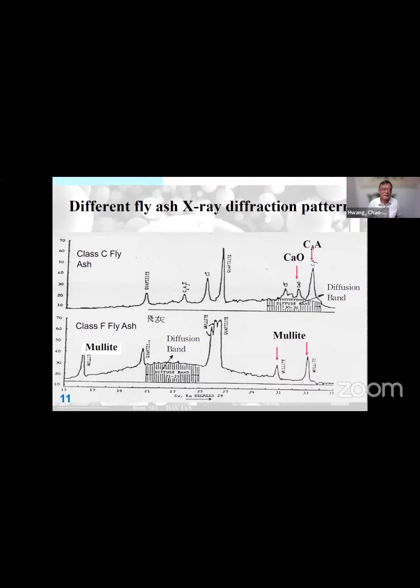Class C fly ash has a diffusion band at about 30 to 34, and class F fly ash has a diffusion band at about 21 to 25. The major composition of class F fly ash, because it contains a large amount of SiO2 and Al2O3, is mullite and some quartz. Next, please.